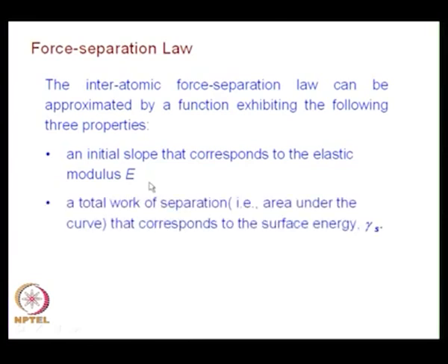And the second aspect is the total work of separation, that is area under the curve, corresponds to the surface energy gamma s. So, what you will have to look at is people who are making theoretical calculation have already brought in the role of surface energy in some other form.